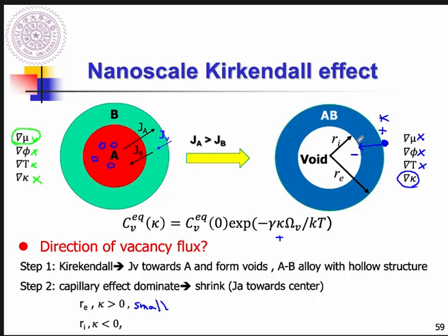However, at the inner concave region, the kappa is negative. Then negative, negative, so in the exponential term you have positive, so you will have a higher vacancy concentration.